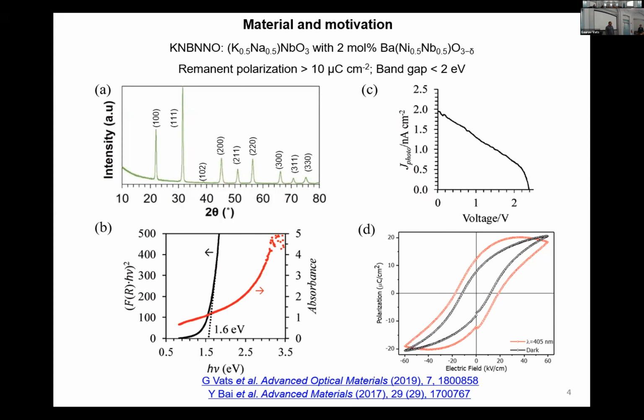Yeah, we did that. I was just trying to show the current density increases when you optically shine light on the sample, and the remnant polarization increases. Is there a correlation between these? Like, we say that in ferroelectrics the current density is the leakage charge. So on shining light, the leakage current is increasing in a way. There are two things. One is actual leakage current. Another thing is when you change the state of polarization, then the current collection is different. So in this material, depending on the time scale, both are happening, or at a particular scale maybe only one is happening. Usually what people do is when they plot this P loop, they actually have this sort of IV diagram as well. And you can actually correlate that. But we haven't done it.